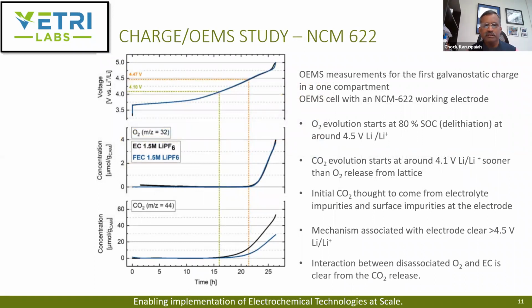The only thing is the mechanism change with the low rate. So the CO2 starts, like to your point, because it's like chicken or egg, right? The oxygen needs to come out, you need the reaction with ethylene carbonate for the impedance, for the degassing to happen, and then the reaction product to happen, and then the impedance to build up. So that's kind of the subsequent mechanistic steps. But then they're saying the CO2 evolution itself starts even before that.